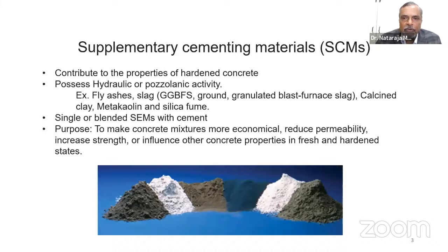Now, these are all the host of supplementary cementing materials, and I have taken this figure from Google. We will be seeing different types of materials as an alternative to cement and as a substitution for part of the cement. These days, people are using these materials. In fact, I already made a mention of fly ash, slag, ground granulated blast furnace slag, calcined clay, metakaolin, and of course, silica fume. Metakaolin and silica fume are the new generation supplementary materials. We need to use them to the extent of about 10 to 15% in the production of high strength concrete. Otherwise, getting strength beyond, say, M60, M70, going up to M100 plus is extremely difficult with the use of other supplementary materials. So silica fume or metakaolin is a must supplementary cementing material as applied to high strength concretes.